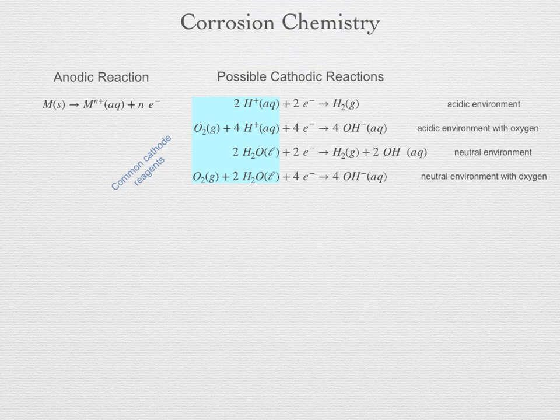The metal cation may remain dissolved in the electrolyte, or, more commonly, it can react to form the metal hydroxides or deposit back as a metal oxide. Notice how the cathode products can be gaseous, H2, or ionic hydroxide. The hydroxide ion concentration will be increasing, thereby increasing the local pH of the electrolyte and contributing to the possible formation of metal hydroxides. More complications can arise.